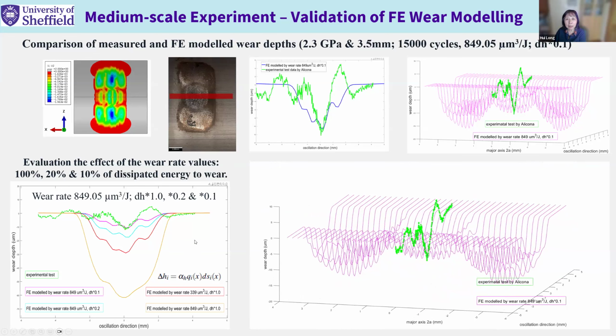However, we found the finite element model overestimates wear depths in all cases. Through evaluating the effect of wear rate values, that means if we consider 100% or 20% or 10% of the dissipated energy to contribute to wear, we are able to find a close match between FEA and experiment measurement.